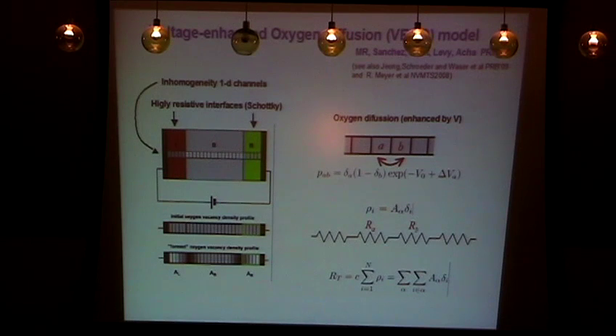You apply a voltage pulse. In each step of your simulation, carriers, in this case oxygen vacancies, will hop from domain to domain, and you recompute all the voltage drops in each one of these things. So you have the fields, and with the fields you recompute how the vacancies move. So it's a very simple model. You can think of this as being really stripped down to the bones, really bringing to light what is essential and what is not. So the total resistance of the system will just be the sum of the resistivity of all these links.